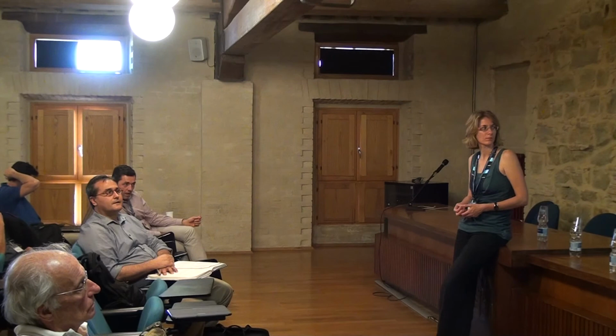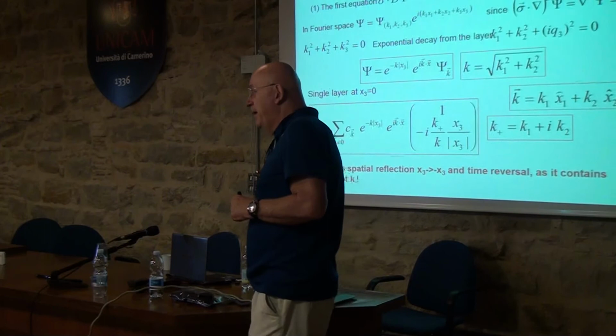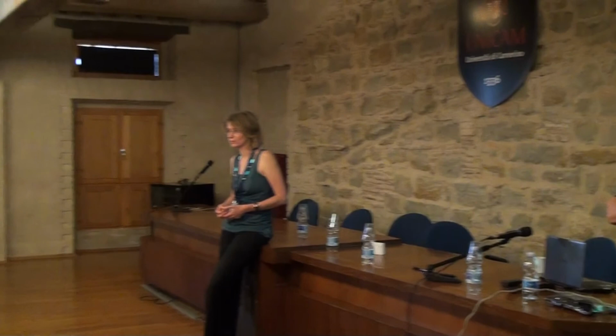The psi breaks spatial reflection and time reversal. So it's a chiral density wave. There are propositions for the pseudogap in the cuprates with chiral density. It's a chiral density wave. But you see, I can have many chiral things here. It's a tremendous degeneracy, so you can have many solutions with this chiral breaking. But for example, if you have a d-wave charge density wave, then simply by the orbital effect you generate a d-xy component, and then it becomes chiral. And then you have this kind of diamagnetism that is not associated with the superconducting state.